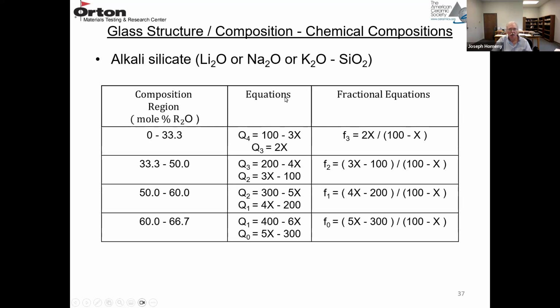So you can also develop equations to calculate Q4, Q3, Q2, and Q1. So these are the compositional ranges in mole percent R2O, whether it's Li2O, Na2O, or K2O: 0 to 33.3%, 33.3 to 50, 50 to 60, and 60 to 66.7%. So that would be the mole percent of R2O compounds. These are the equations, and then these are the fractional equations.